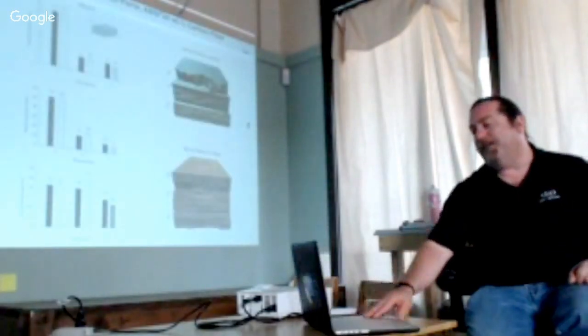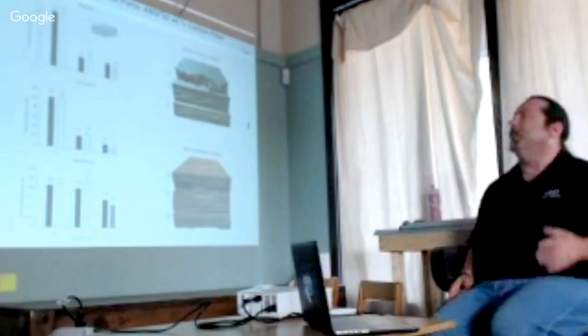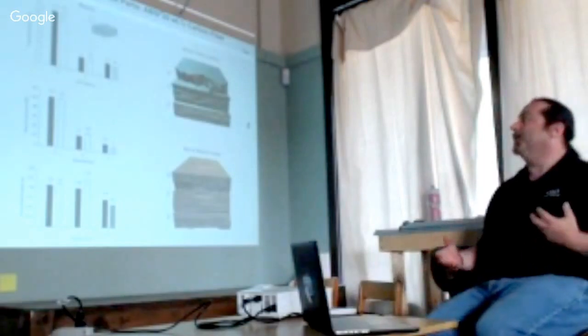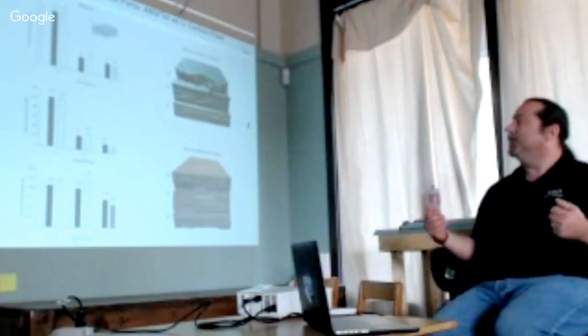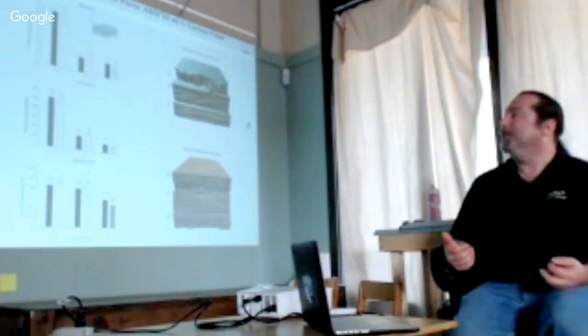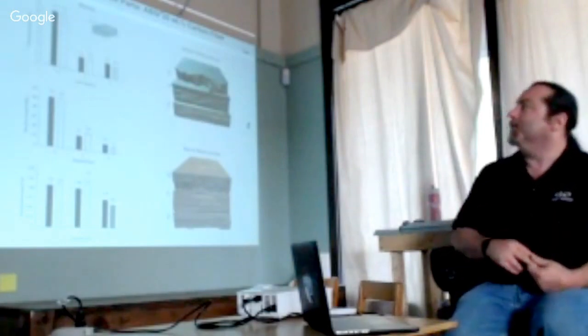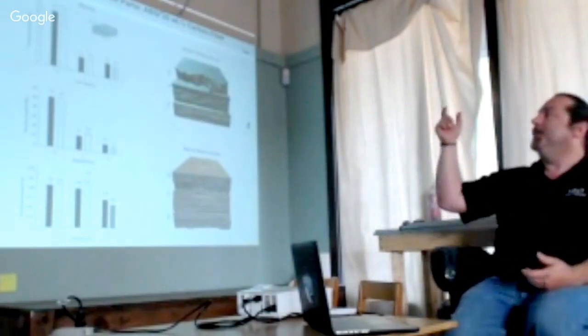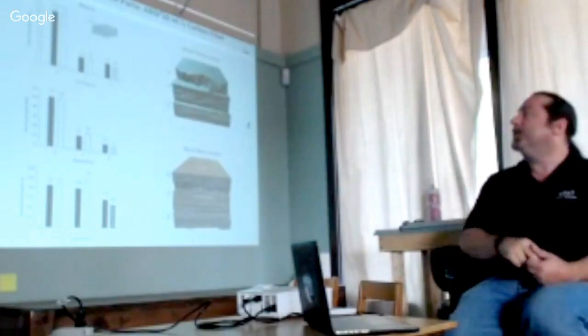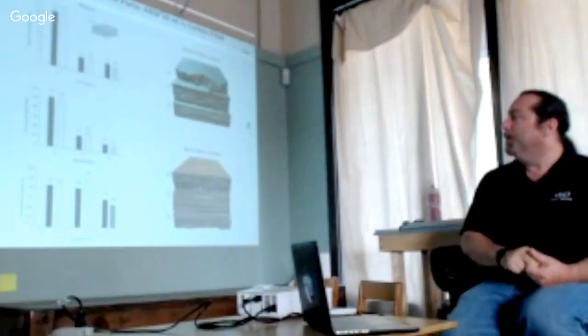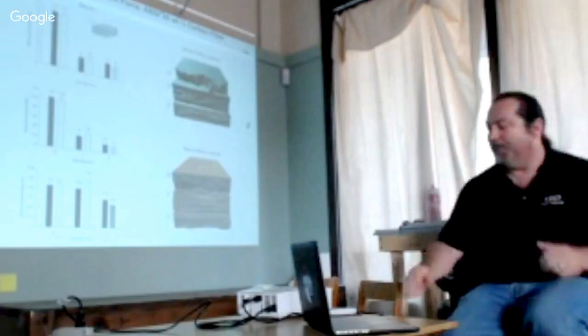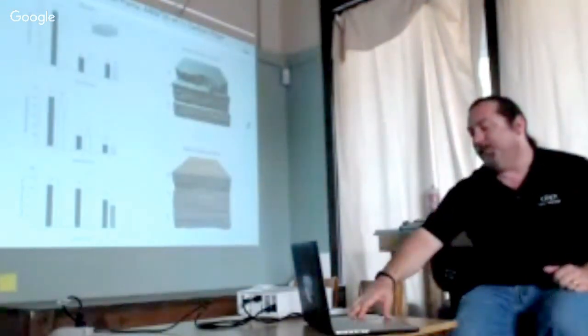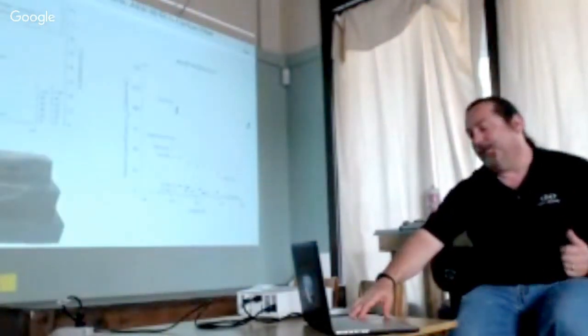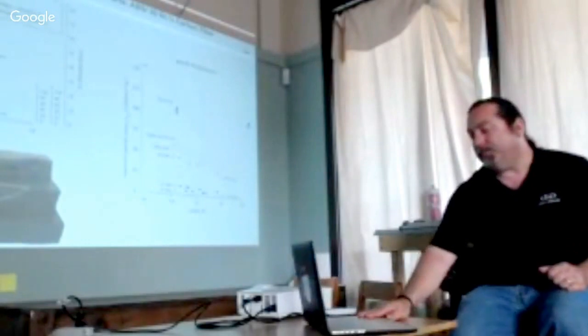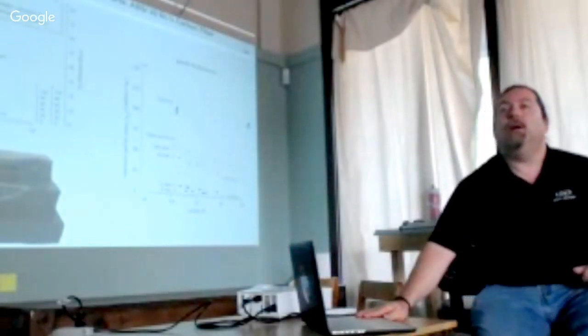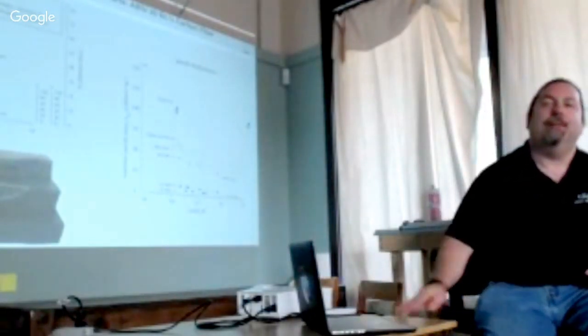So you can see it's about 3 times both the strength and modulus in that X direction versus the Y and Z direction. And then you can also see, as a function of time between layers, here this shows 5 and 10 minutes between layers, so the strength drops as a function of time, and we've done some further studies with that. Can you heat it up or go back to like a warm mold?